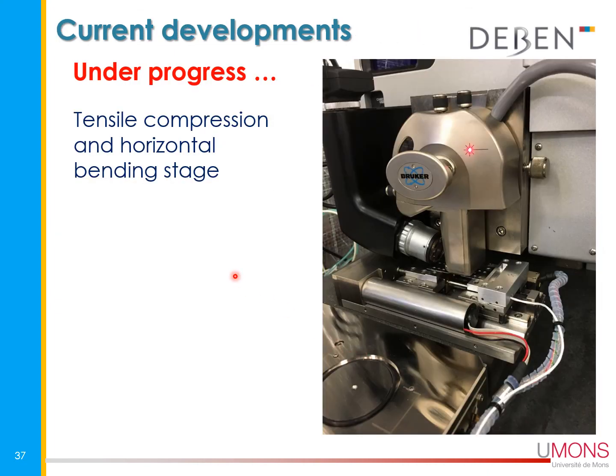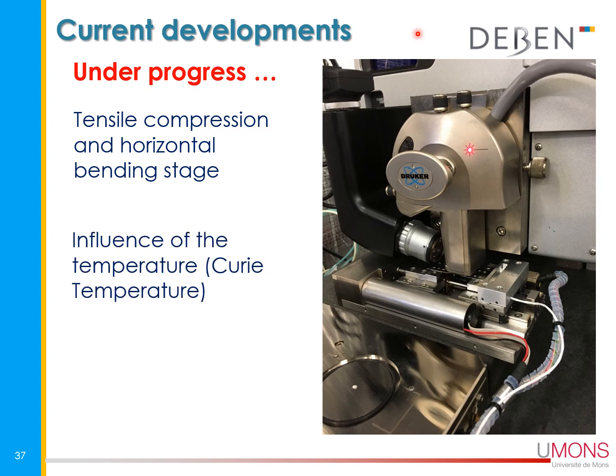What is also still ongoing for the moment is to apply tension, compression or bending on the sample just below the AFM tip, and to modify the sample and to see, by just flexing the sample, if we are still able to measure some piezoelectric properties. We would like also to measure the influence of the temperature, and to see if, for instance, we have the Curie temperature of the system, and to see the evolution of the piezoelectric properties with the temperature, by modifying the temperature of the sample.